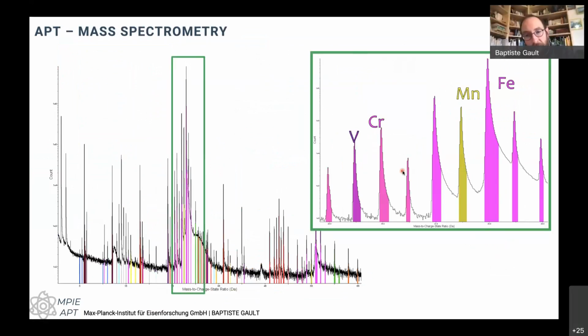It's a good question. We assume that these elements have their natural abundances. Within a peak where there's an isobaric overlap between chromium and iron, I cannot determine what it is for every single ion. But if I take a small volume, I can do a statistical analysis and say, I know that within this one peak where there is an overlap, 5% of the peak should be chromium and 95% of the peak is iron. Then I can derive the number of chromium and iron atoms separately.